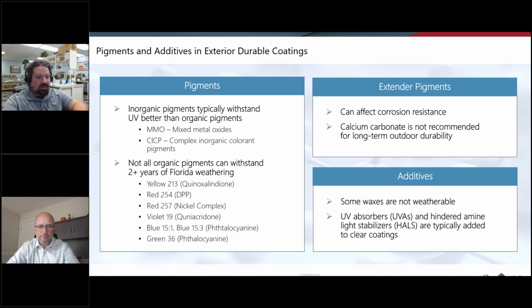And then additives. You can improve your weatherability a little bit using UVAs and HALs. They work a lot better in a clear coat than they do in a pigmented system, just because they get physically blocked by pigment particles, and if they're not available, then they're not going to give you any properties.